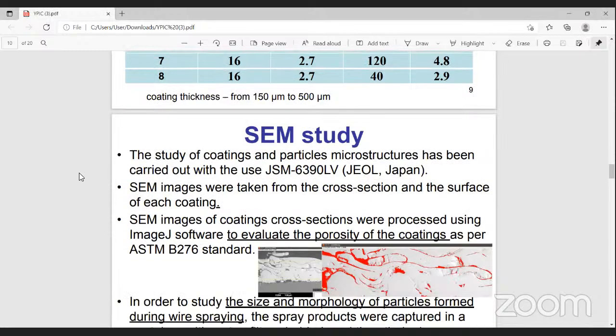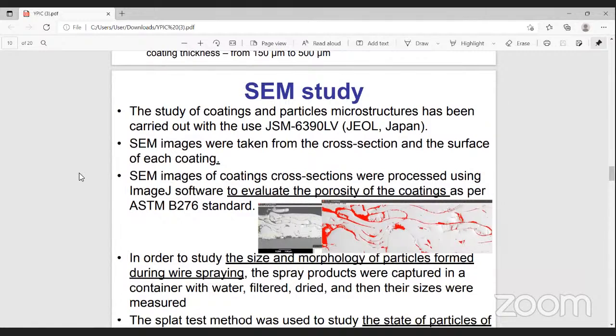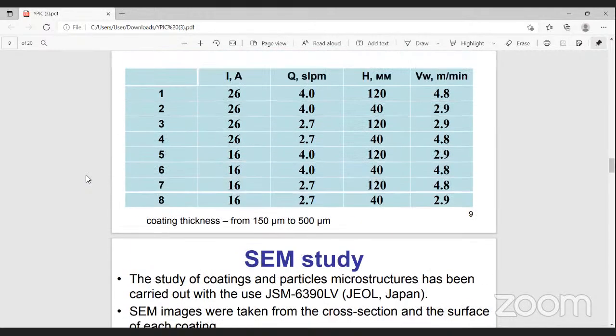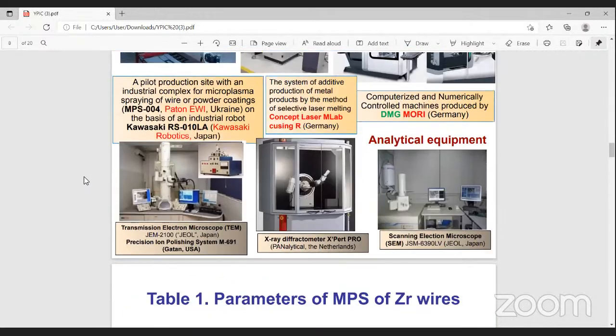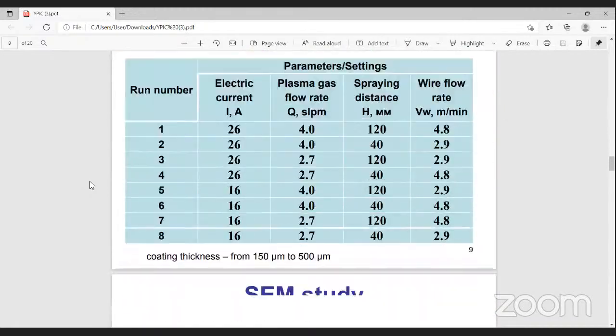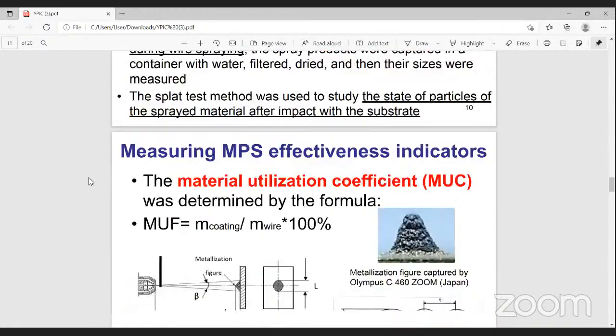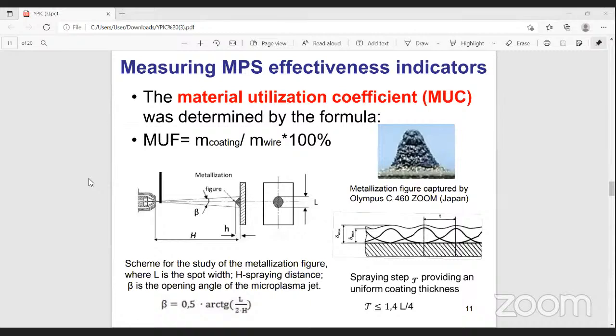The study of coatings and particles microstructures has been carried out using the instruments shown here, and by processing the obtained images, the coordinates of at least 20 points of the line forming the profile were determined.